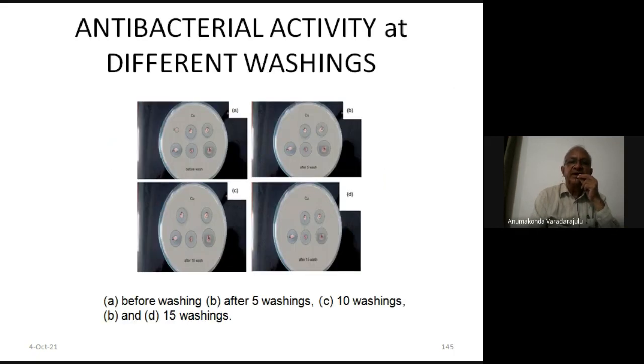They showed very good antibacterial activity even after different washings. She washed these fabrics for different times, 5 washings, 10 washings, 15 washings, but they retained their antibacterial activity even after 15 washings. That means we can repeatedly use these fabrics either for apparel or hospital bed materials, pillow covers, or even for gloves or aprons, because they're all antibacterial.